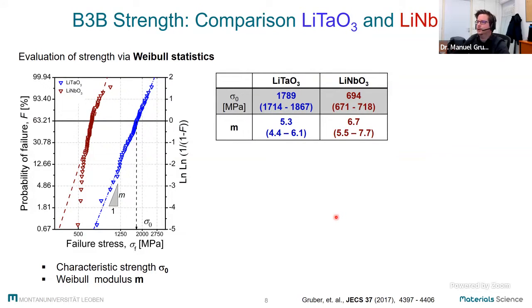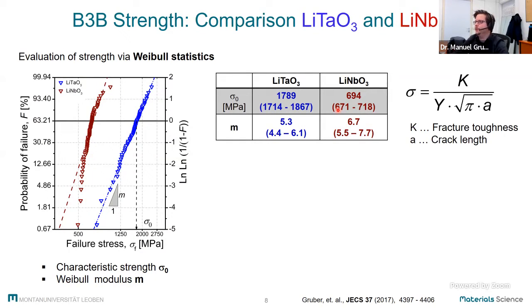If we do the analysis of our characteristic strength, we could see that surprisingly, or at least for me surprisingly, the strength of lithium tantalate was higher by a factor of something like 2.5 compared to lithium niobate. Even though tantalum as well as niobium are in the same group of the periodic table, and both have the same crystal structure. So this is, at least to me, really surprising. There can be two reasons for these differences. So either we have a different defect size in our materials or a different toughness. And I will show you today that both of these things influenced or were the reason for the big difference between the two materials.